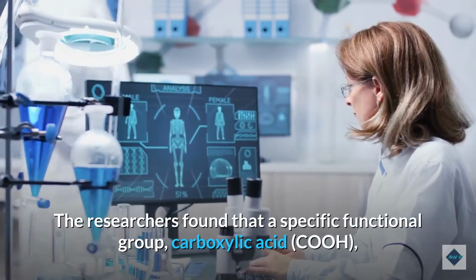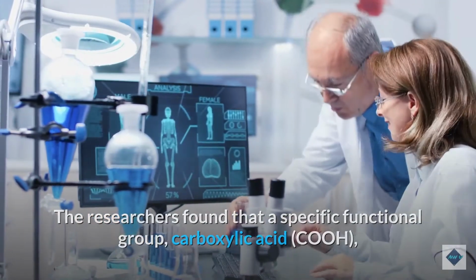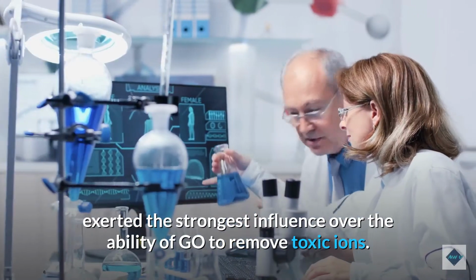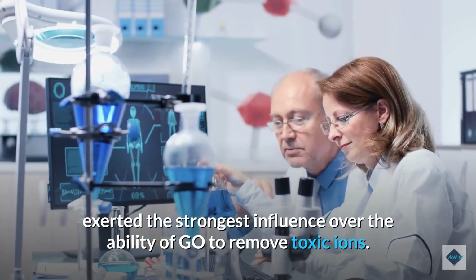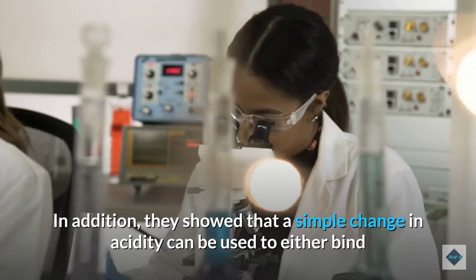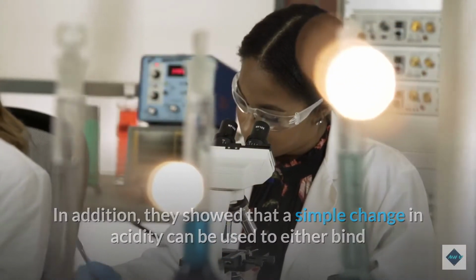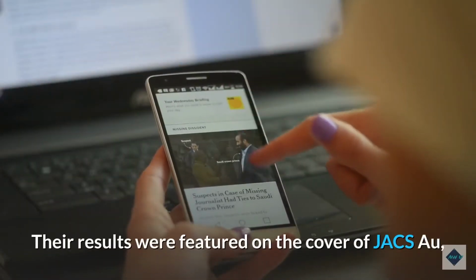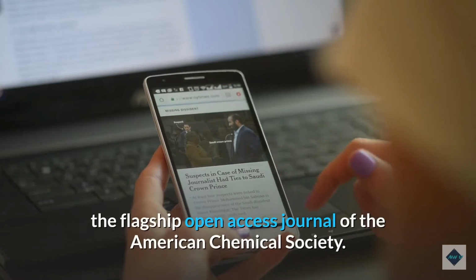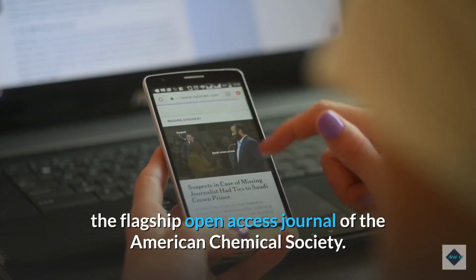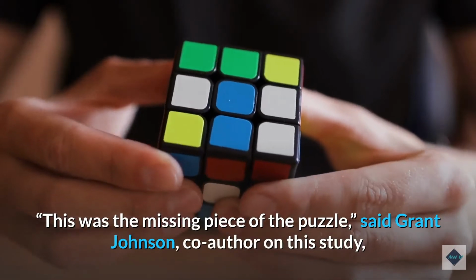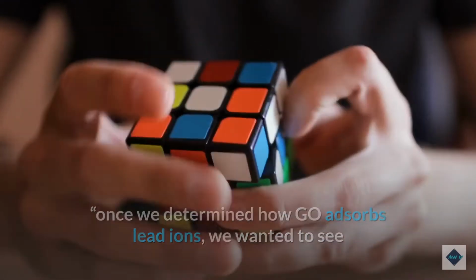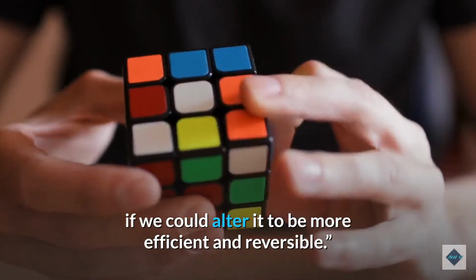The researchers found that a specific functional group, carboxylic acid, COOH, exerted the strongest influence over the ability of GO to remove toxic ions. In addition, they showed that a simple change in acidity can be used to either bind or release the lead ions from GO, making the material reusable. Their results were featured on the cover of JACS Au, the flagship open-access journal of the American Chemical Society. "This was the missing piece of the puzzle," said Grant Johnson, co-author on this study. "Once we determined how GO adsorbs lead ions, we wanted to see if we could alter it to be more efficient and reversible."